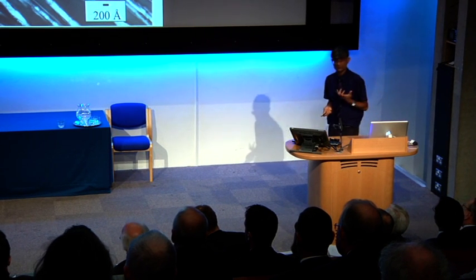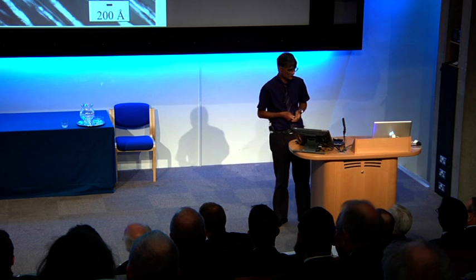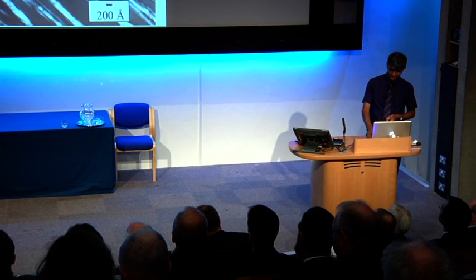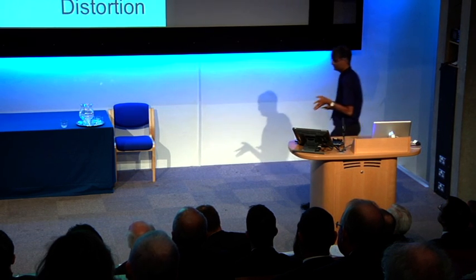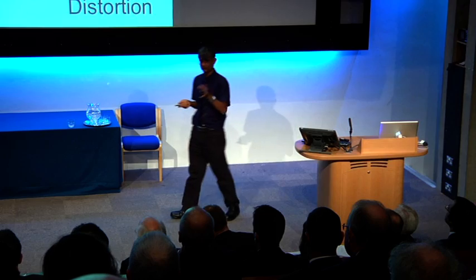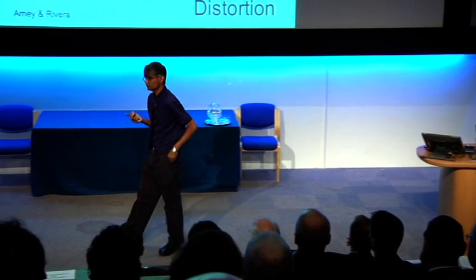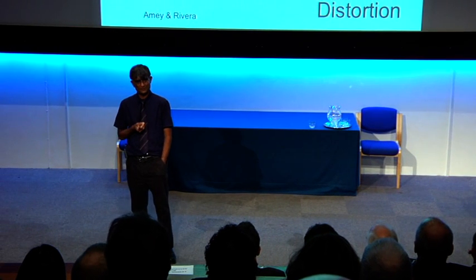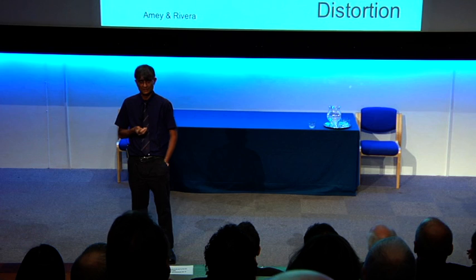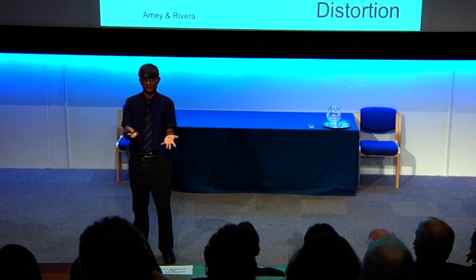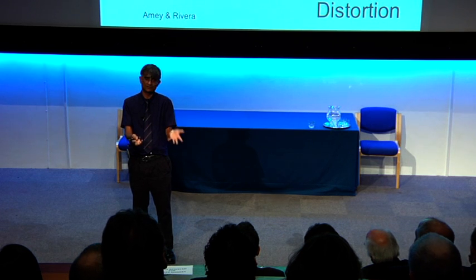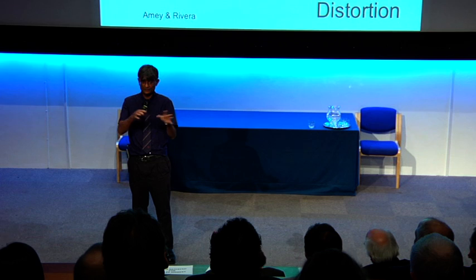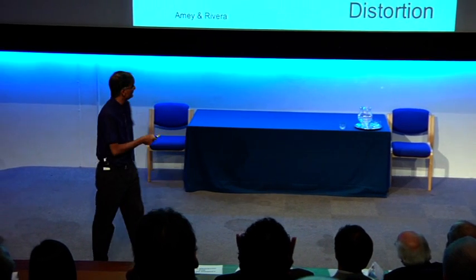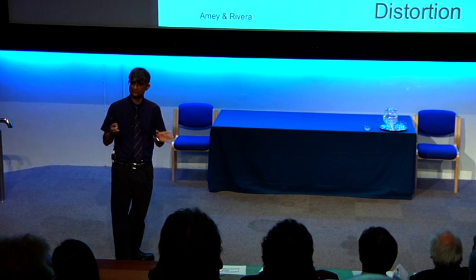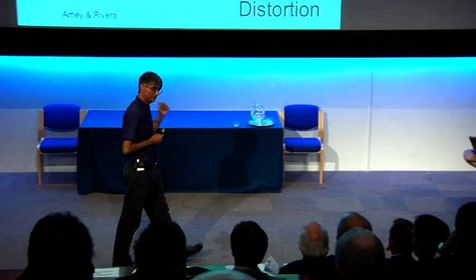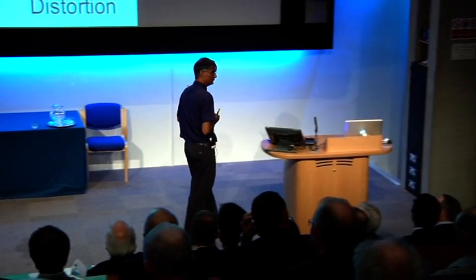And it's very cheap. Okay. There's no new technology required to produce this. And it's uniform in large sections. And this is not all the results we have, but this is work done by Chris Amey, who is somewhere in the audience, and Pedro Rivera, where we can show that the distortion due to the phase transformation itself, when you do the heat treatment, if you have a material in which there's a temperature gradient, then transformation will start first in one region and then in another region, and that develops a system of stresses. But if you can start the transformation uniformly everywhere, you have very little distortion. Of course, there are many, many mechanisms of distortion, but this particular mechanism is more or less eliminated.